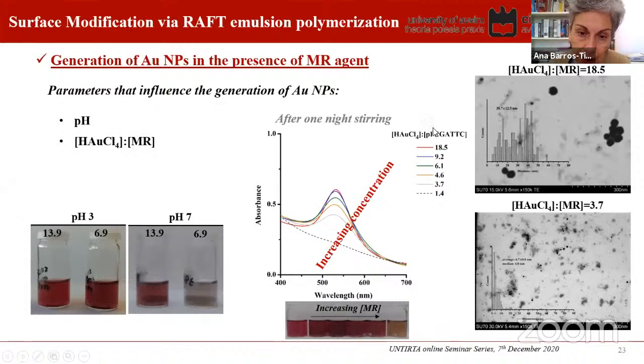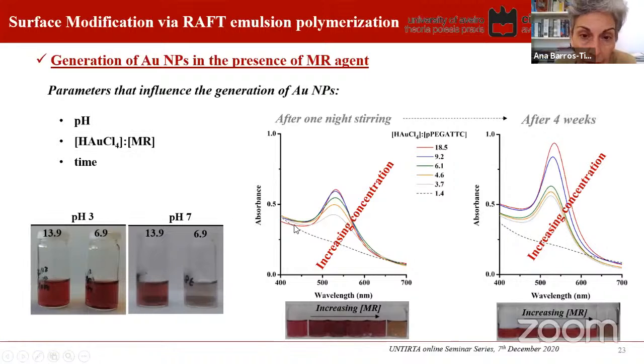So we realized that, in fact, the ratio of the gold precursor to the macro RAFT had a major impact. Also, working at pH 7 or at pH 3, for example, caused a significant change in the size of the particles that were obtained, and of course, in the aggregation level. Also, the time had a major impact.